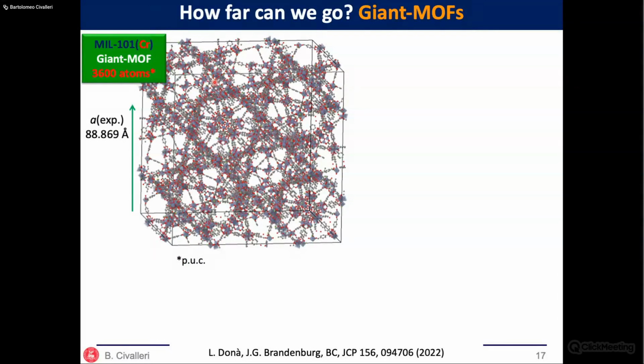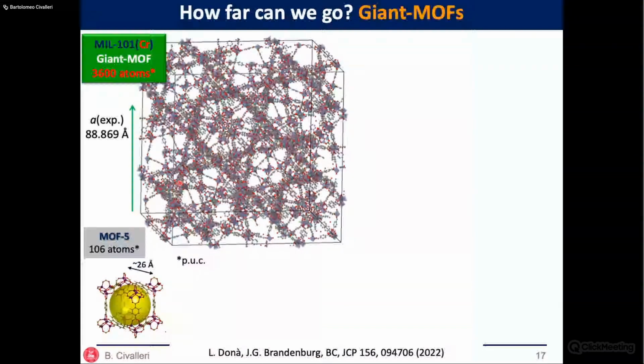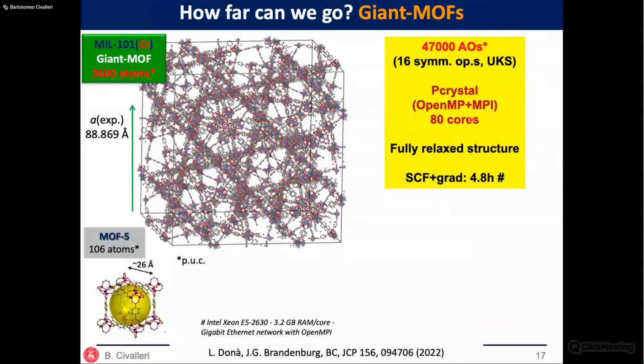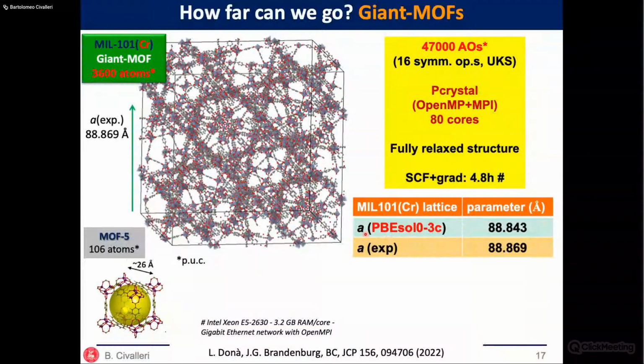The question is, how far can we go with studying these MOFs? These are very exciting results that we had applying our composite method in the study of a giant MOF that contains almost 4,000 atoms in the unit cell. You can see this unit cell is huge, about 9 nanometers for the lattice parameter. This is a comparison with the previous one that I showed you, this MOF-5 with just 100 atoms in the unit cell. We were running the calculation on very small computing resources, just 80 cores with a parallel version of CRYSTAL. We were able to fully relax the structure with one of our composite methods, and we had very striking results in the comparison of the predicted lattice parameter with respect to the experimental one.